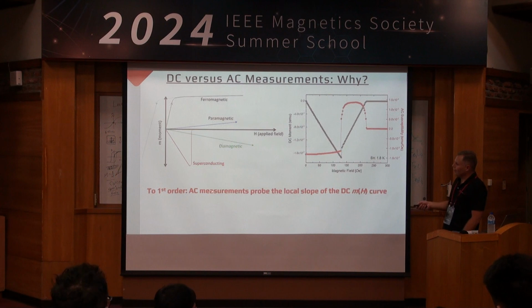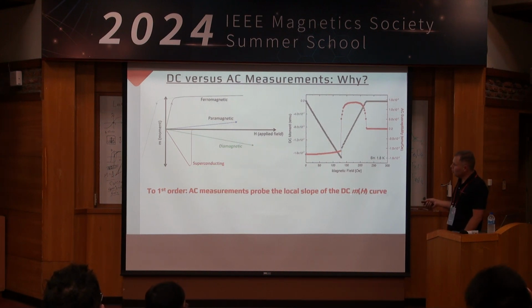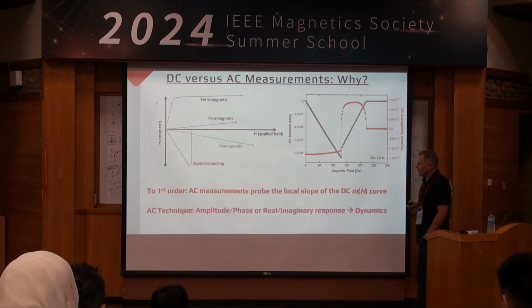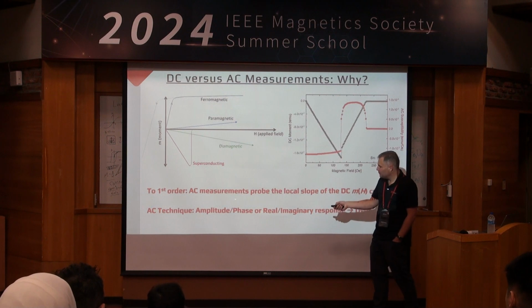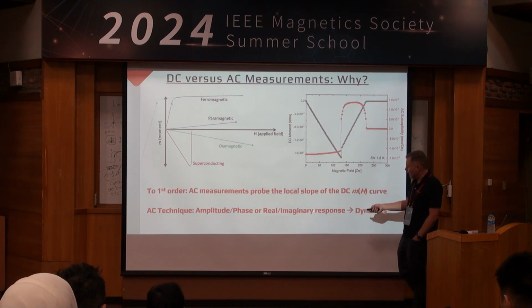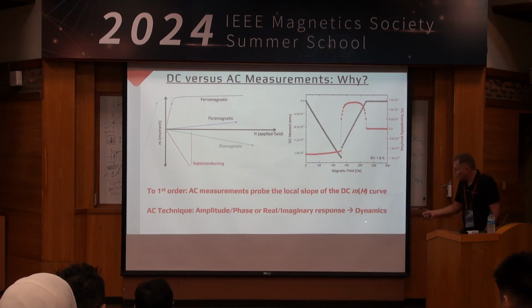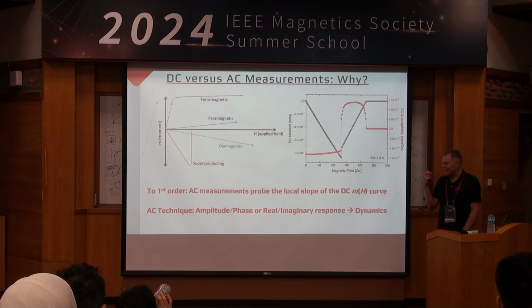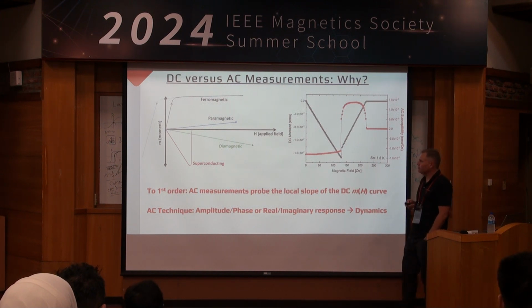To first order, an AC measurement probes the local slope of a DC measurement. So you can see, you can just go through the experiment here. The red data is the AC susceptibility. It's just the slope of the black data here. But because it's an AC technique, we're actually always measuring an amplitude and a phase, or a real and imaginary response. And therefore, we're intrinsically measuring the dynamic response of our sample.